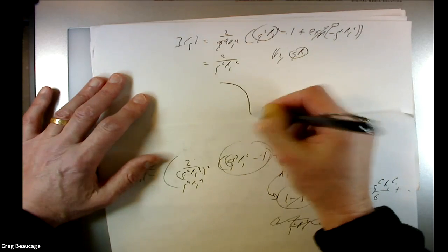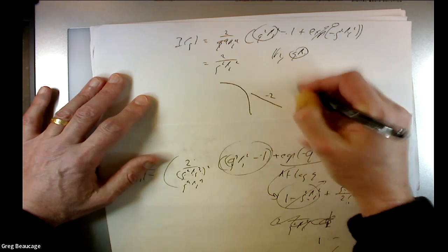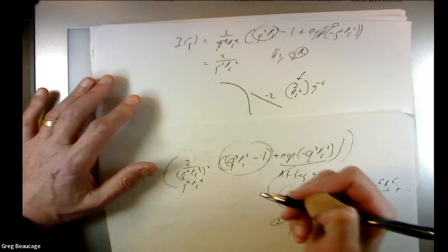And then this thing cancels with this, so you end up with 2 over Q squared RG squared, which is our power law. So we have Guinier's law, and then we have this minus 2 law, where we have 2 over RG squared times Q to the minus 2. And so that's our power law prefactor. It's just kind of like 2 ways to get the radius of gyration of this thing. There's a contrast factor in front of this, and so this I naught goes out in front, which is basically going to be how many polymers are in a thing, and then the electron density of the polymer squared.